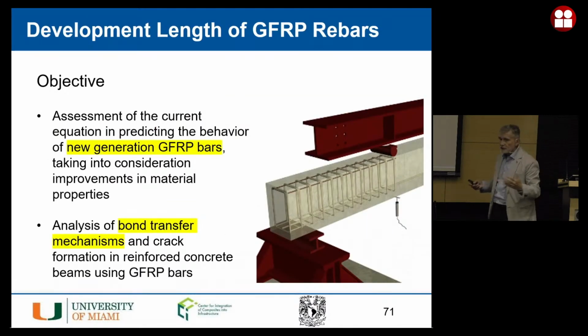The next one is a very interesting study. One of the limitations of these materials is related to the fact that bond is not as good as in the case of steel. Why? Well, if you think of the surface of a steel bar, you have the ribs, right? And then the mechanism of stress transfer is because of mechanical interlock. So the concrete, if you were to pull the bar, the steel rib will push against the concrete, and then obviously of the two, you eventually crush the concrete. Okay, either because you slip, or because you have cracking, or because the splitting governs, but you never destroy the